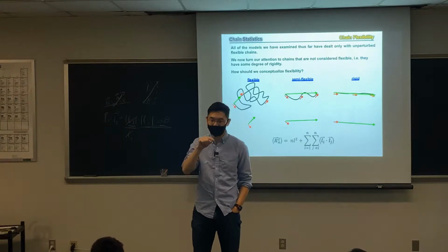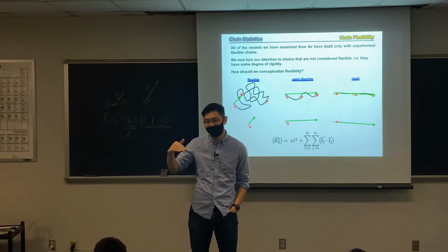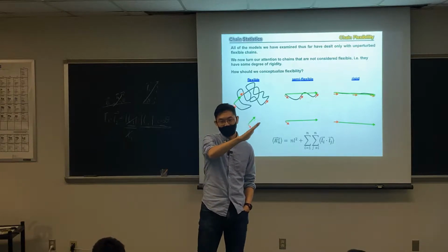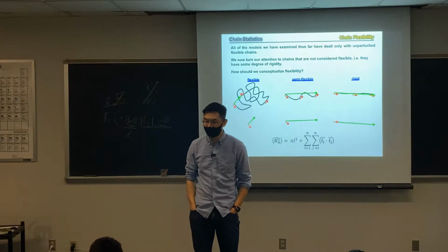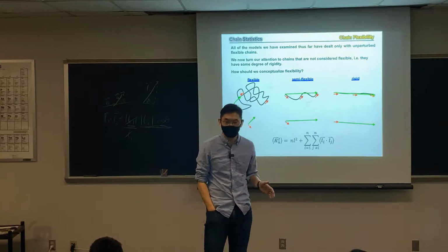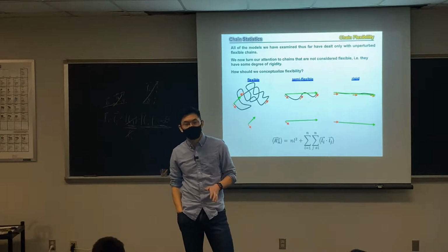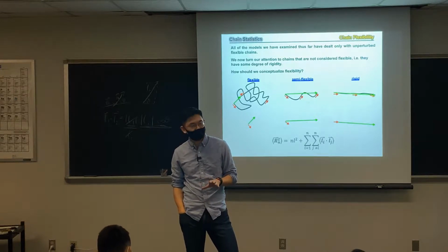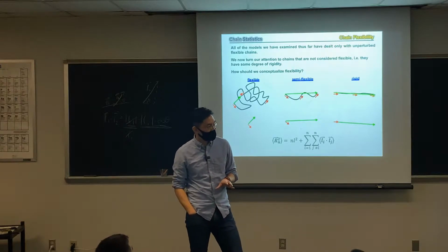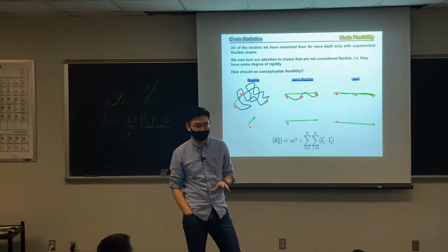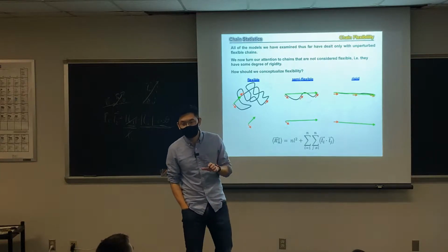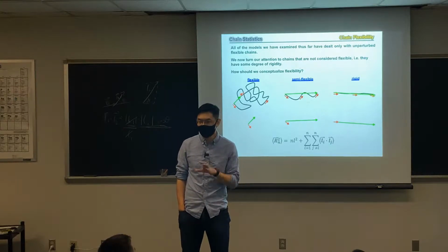If you think of a free rotation chain with a bond angle of 109 degrees, one bond is going to be bent slightly, and then the next bond will be able to reach that. So if we look at the persistence length with a bond angle of 109 degrees, that will be equal to the characteristic ratio, roughly about 2, what we have calculated, right? So your persistence length will be roughly the characteristic ratio divided by 2 multiplied by L.